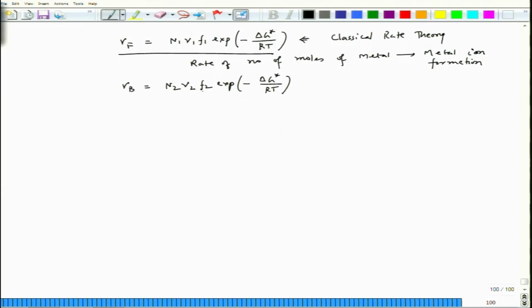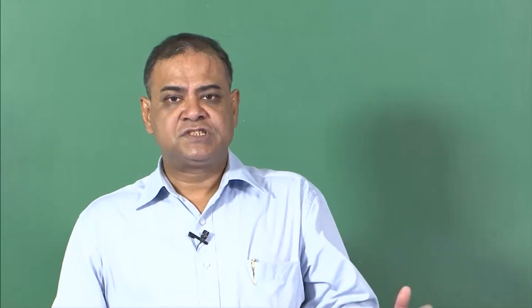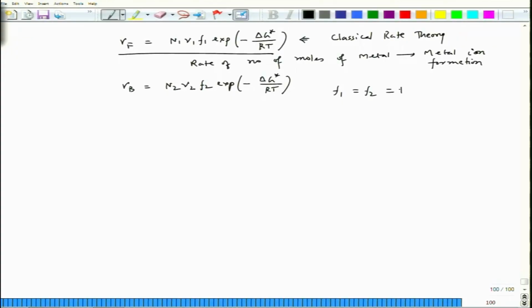Now, if I consider that whatever metal atom goes to the metal ion surface, everything gets absorbed there, or the metal ions which are getting reduced, they all will deposit on the metal surface. So, then F1 equal to F2 equal to 1. Since this is a fraction, this becomes 1, because whatever metal ions are forming, they are going to the OHP, or whatever metal ions are reducing, they are going on to the IHP. Now, nu 1 equal to nu 2 is of the order of 10 to the power 13 per second,